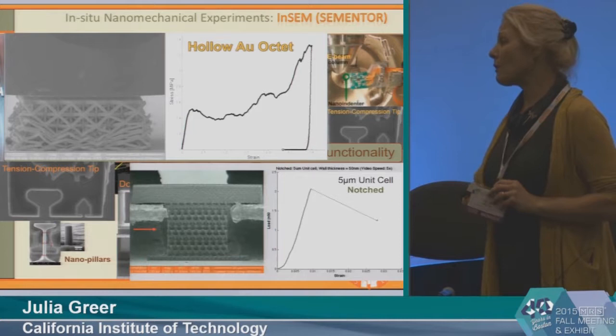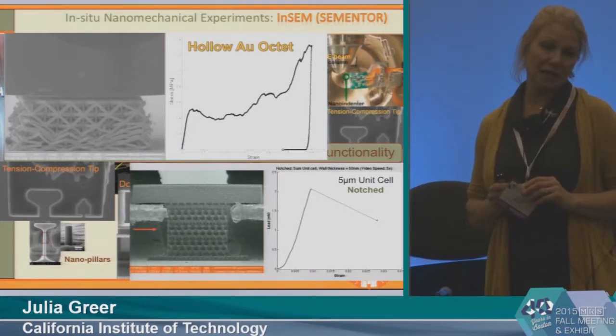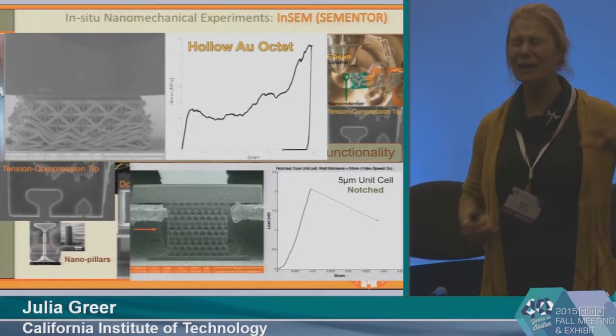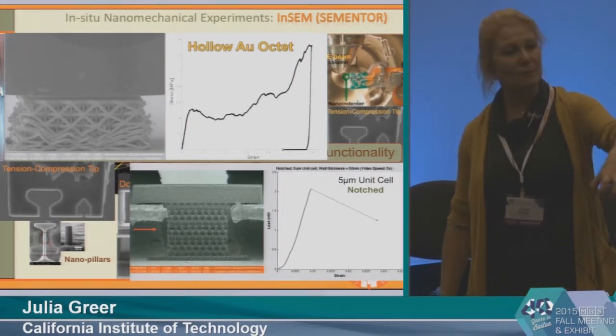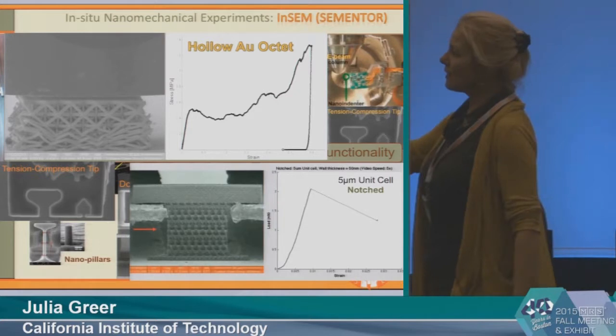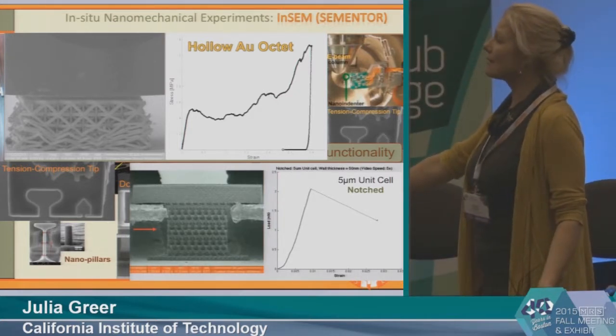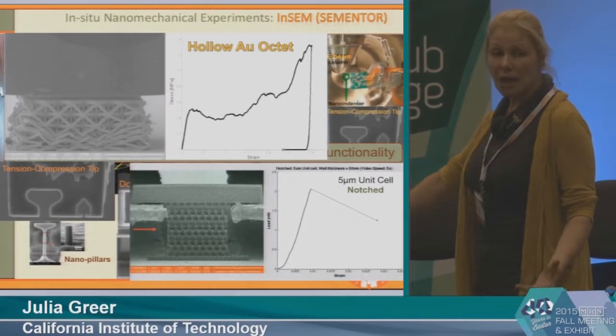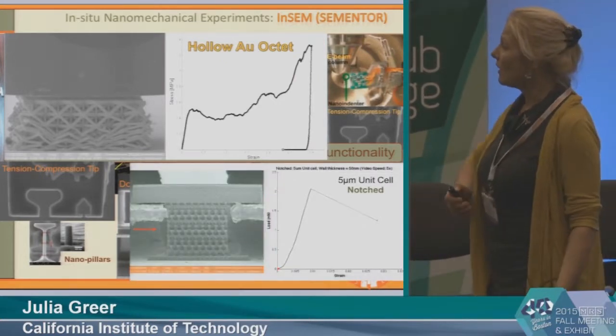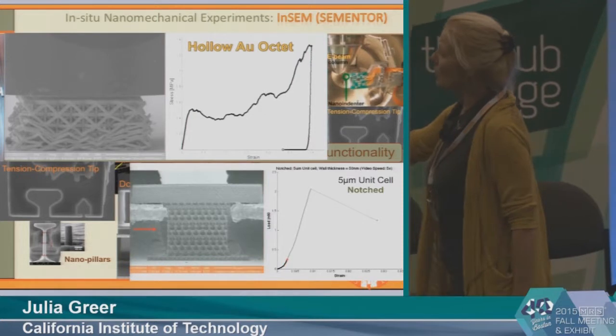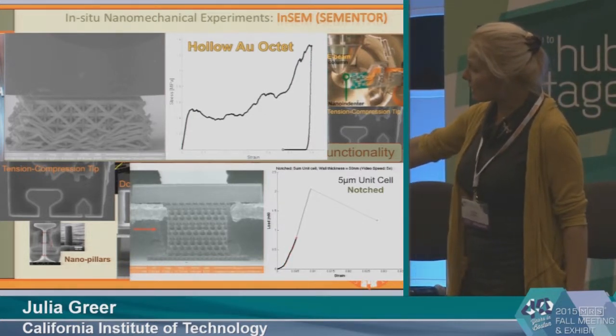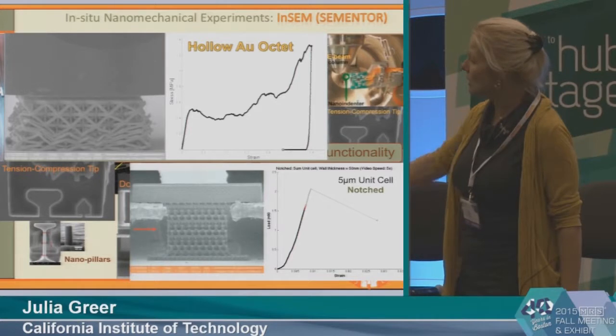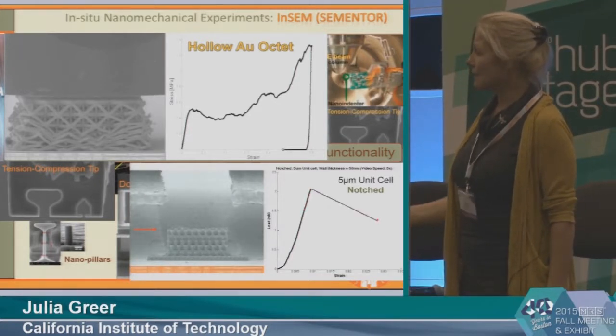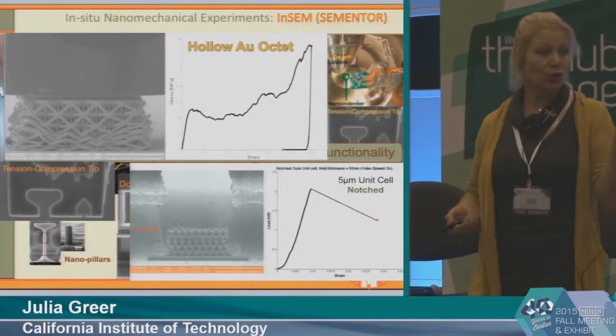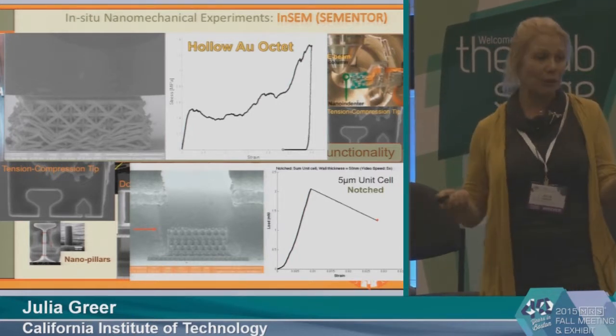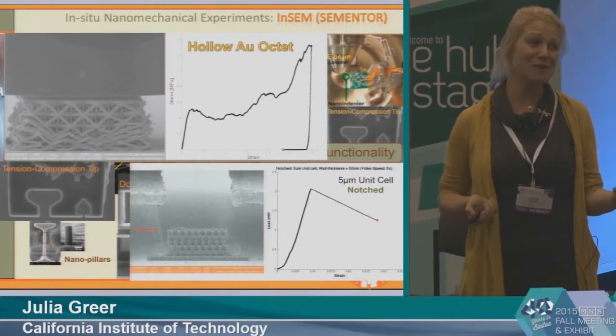Now, probably one of the main powers of this particular technique comes from our ability to do tension testing. So compression you can do blindly like this, but for tension you have to be able to grip your materials. And so this is one of these nanolattice type samples, which has a pre-fabricated notch in it. We wanted to understand its sensitivity to flaws. And so yet again, the same person, Lauren, is doing this experiment. So she's pulling on it, and you can see the crack that's opening up here, and you can see the loading curve. And at the same time, eventually you see the failure that occurs along this crack. And you would never know where the failure occurred or how it occurred without the ability to see it. Not to mention you'd never be able to grip it.